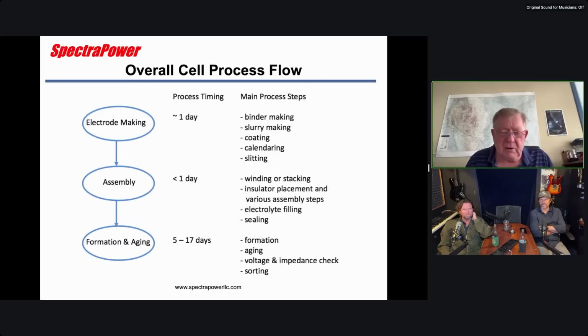Back in the day, Sony would do it for 3 weeks. And the reason you do this aging is you charge the cell. Remember, they're built discharged, so you charge it, and then you store it. This is where battery factories typically burn down, and almost everybody has had a fire. The reason you age the cell is you want to let any internal defects show up, and usually they show up by exploding or catching fire. When we were manufacturing cells here in Livermore, it wasn't unusual for us to have 1 or 2 cells blow up in the aging racks. And so you usually would have some kind of fire suppression. Then you do a voltage and impedance check, and you sort the cells according to capacity and impedance.